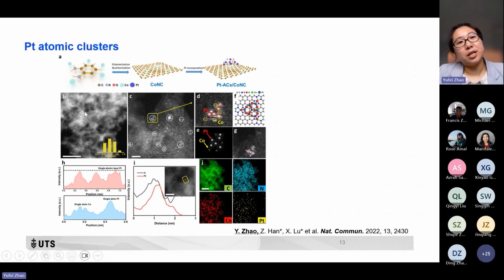After we obtain this material, we have to do the characterization. We can see there are no particles here. That means all the platinum has been maintained as atomic clusters. The diameter is lower than 1 nanometer. And also when we zoom in, we can find different contrast of the bright dots. The higher contrast we ascribe to platinum, and the lower contrast we ascribe to cobalt. When we look at one atomic cluster here, we can also find different contrast of the atoms.